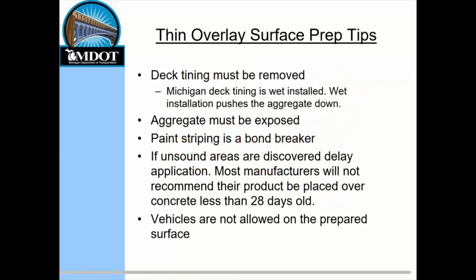And it's for that reason that in Michigan, we require our deck tining to be removed. All of our deck tining is installed wet, and it is our belief that the wet installation of the tining will push the aggregate down. So if you're not removing your tining and you're installing your tining wet when you're pouring your deck, then you're not getting as much aggregate exposed and you're not getting as much aggregate to adhere to.